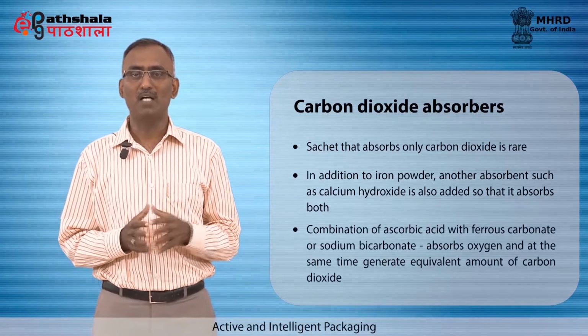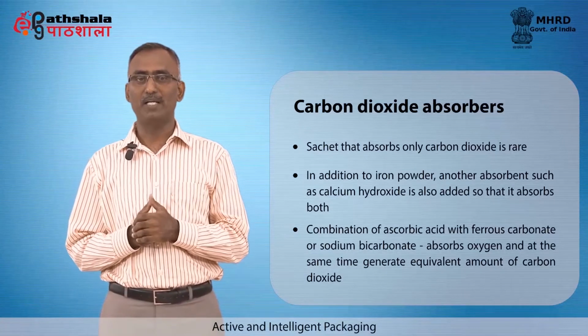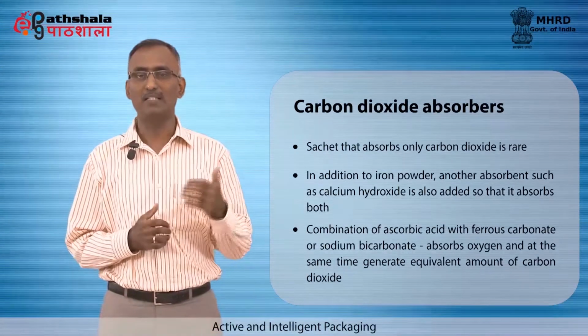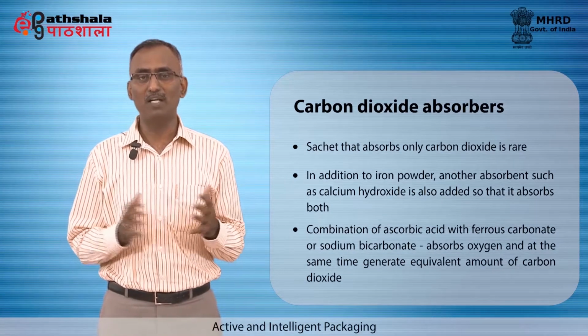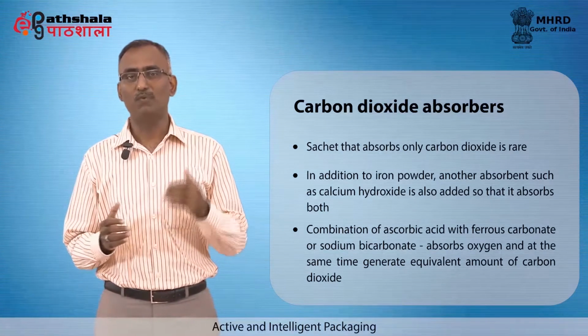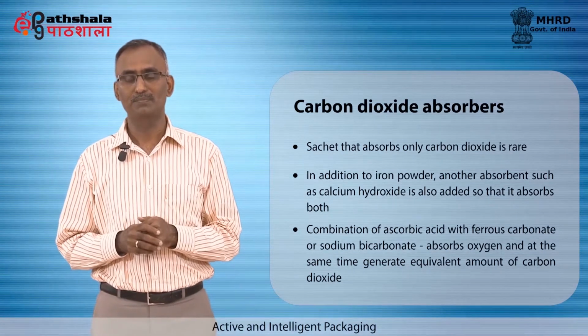The combination of ascorbic acid with ferrous carbonate or sodium bicarbonate is also available, which absorbs oxygen and at the same time generates an equivalent amount of carbon dioxide. This avoids package collapse if only oxygen is removed.